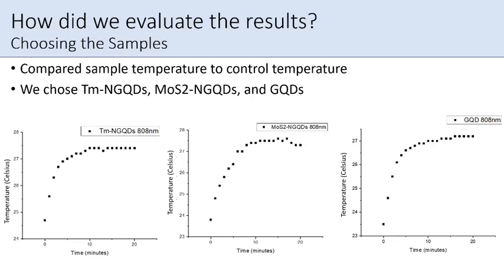Then we started looking at our samples. So for our thulium NGQDs, our molybdenum disulfide NGQDs, and our GQDs, we decided to choose these to work with because the thulium, we see a 2.7 degrees Celsius change. It's not quite the 5 that we're looking for, but we thought it might be enough that we would see some denaturing of the proteins in those cells and that we might be able to cause some damage to the cells. For molybdenum disulfide and the GQDs, we see a 3.7 degrees Celsius change. Again, it's not the 5 that we're looking for, but we thought it might be enough, and so we wanted to give it a try.